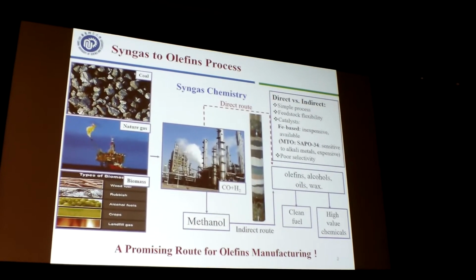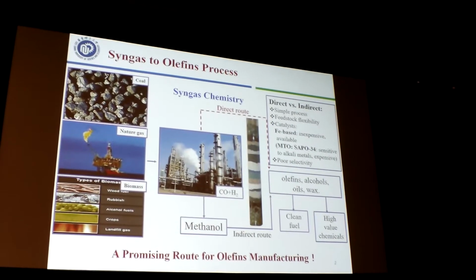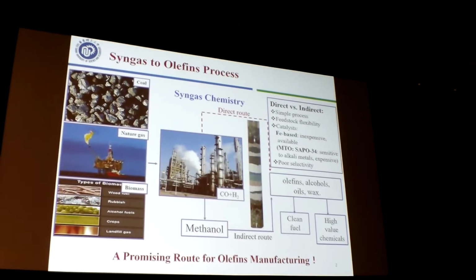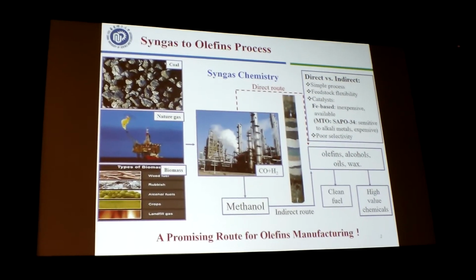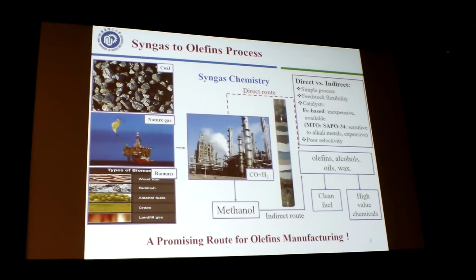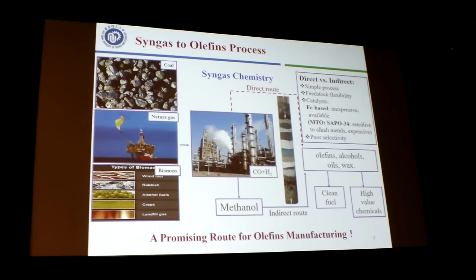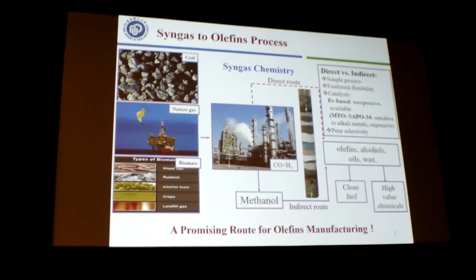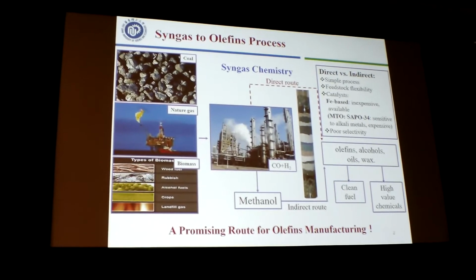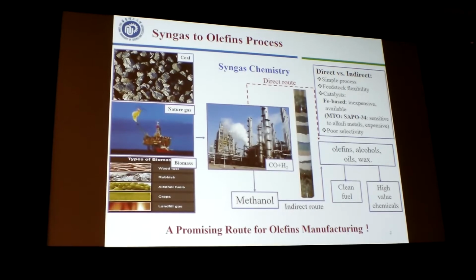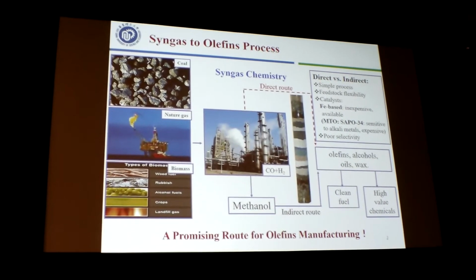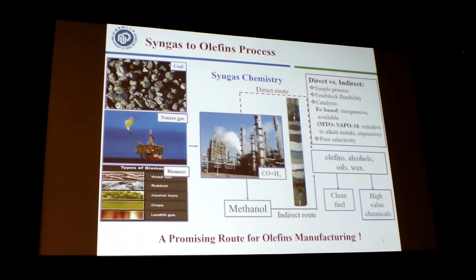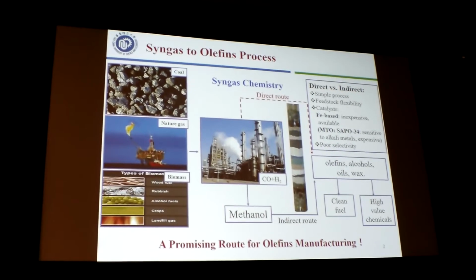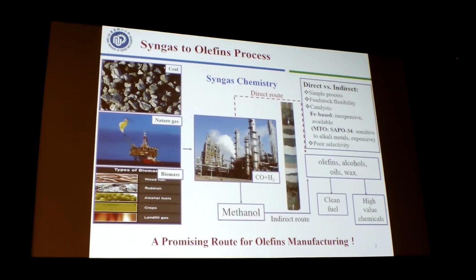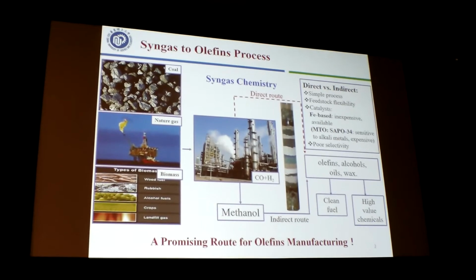As we all know, the indirect route with methanol as the intermediate has already been commercialized. But research on the direct route is still a hot topic, because compared with the indirect route, it has a simpler process and higher flexibility. But it also has some drawbacks. One of the main drawbacks is that the product selectivity is very poor, because it is limited by the classical ASF product distribution. But anyway, the production of olefins through the direct FTO process is very promising.